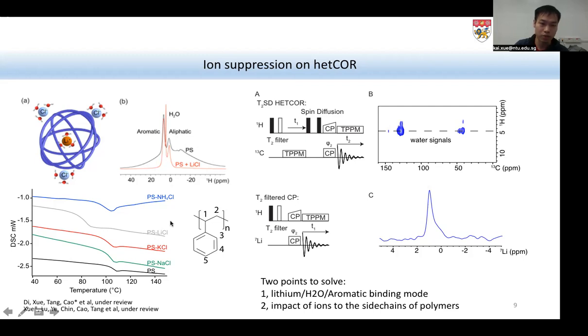This is very different from other salts. So our guess would be that the reason for this large change in the glass transition temperature is due to the introduction of ions that also carry water inside of the polymer. To prove that, since this is a three-component system, we have water, we have polystyrene, we have lithium.